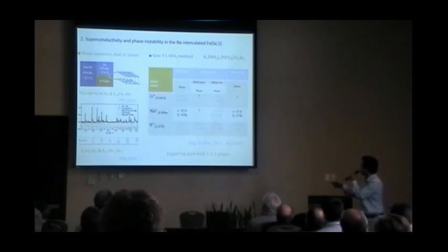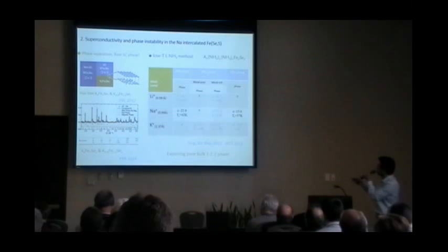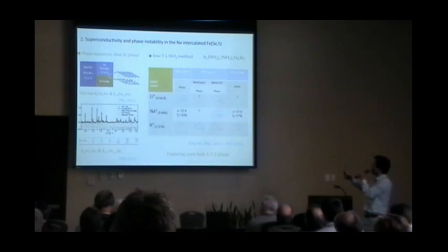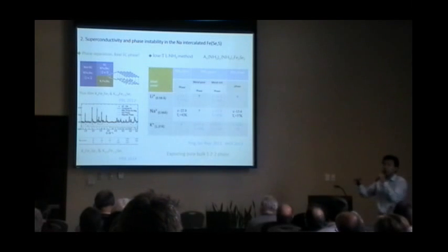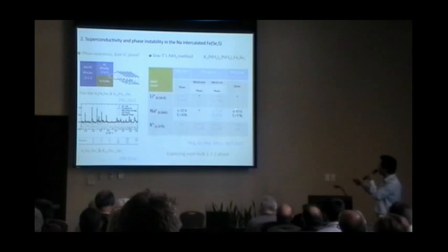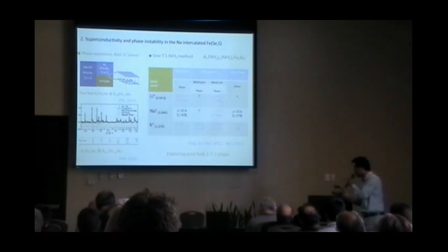is the superconducting phase. So we did some work, you can see this color change, right? Change to black. So we did some work on the sodium system. We found there are two more phases shown here. One phase shown here is the ammonia-free phase. Even though we use ammonia, we didn't find any ammonia in the sample. So we call it the ammonia-free phase. This one is the 1-2-2 phase. It should be the real superconducting phase.